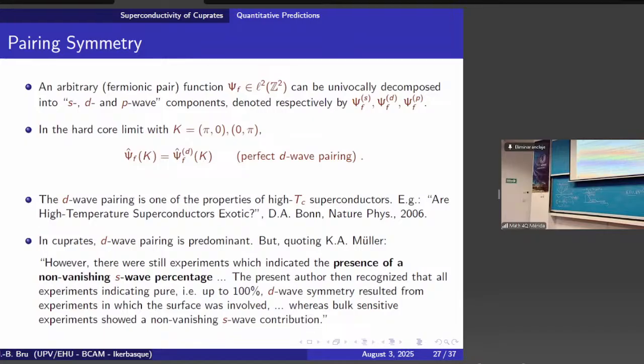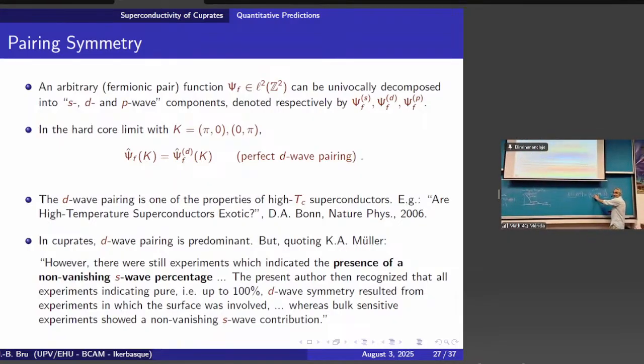So what we will do is compute this, and we try to compute the symmetry of that function. This function can be decomposed in S wave, D wave, P wave. There is an easy way to decompose this in 3 components. Then you look at whether this has an S wave or D wave, or what is the proportion of S, D wave or P wave. P wave means that when you make a rotation by pi, you get -1. D is when you make a rotation by pi over 2. And S is any rotation between 0, pi over 2, pi, 3 pi over 2, it is isometric. This is S.